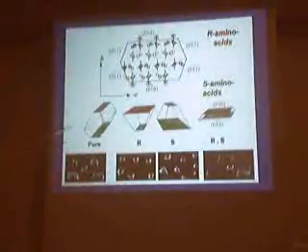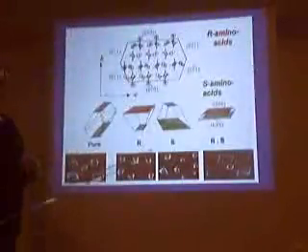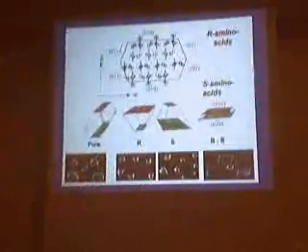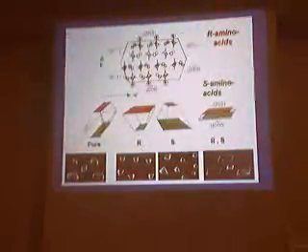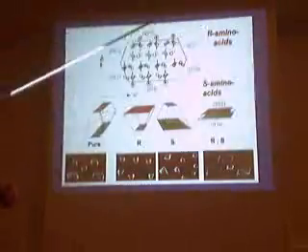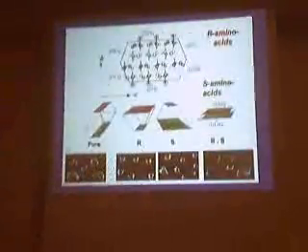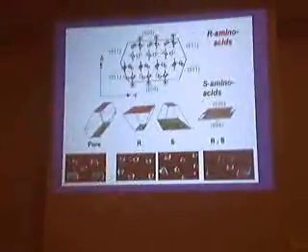But here what we have, because if you go to the centrosymmetrical crystal, and you know the absolute sense of chirality of each one of the two surfaces, you know that. Because you don't have two pairs, you don't have polar pairs like in enantiomorphous crystals, you have just one. If you replace two molecules, you're going to get a different crystal, which you can determine by X-ray crystallography. And therefore, by comparing the morphologies of these crystals, we were able to tell the absolute configuration of the R and S amino acids on an absolute scale. This was one of the side problems of that.